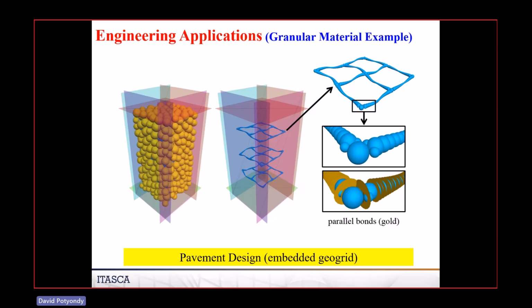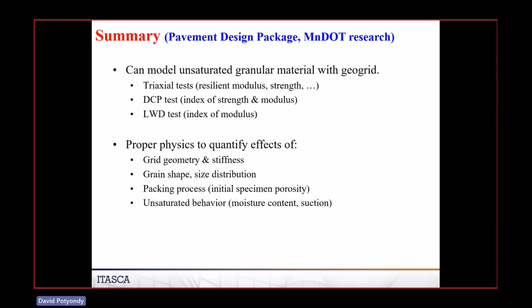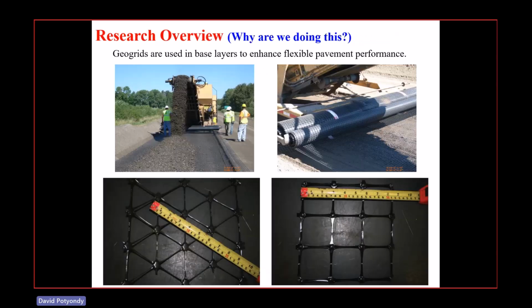So we had a way, when we construct this, of controlling the initial porosity. And what we find is, what effect does that have on the strength? Again, the more porous, the weaker it is and the less stiff it is. And then for the unsaturated case, what sort of moisture content, what sort of suction are we getting? What effect does that have? Those are the things that we were able to quantify with the model.